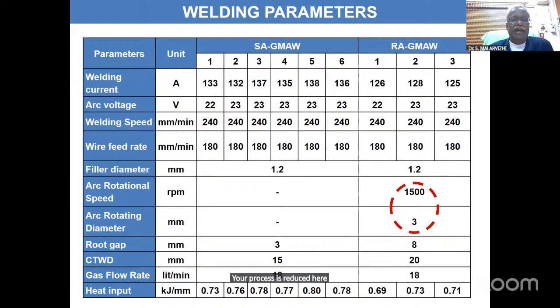And if you see the macrostructure of these two joints, the weld metal area in the stationary conventional GMAW is 205 mm square, but in the rotating arc it is 90 mm square, because only 3 passes are involved. Similarly, the heat affected zone area also reduces from 68.7 mm square to 22.6 mm square, so it reduces to one third. And the number of passes came down from 6 to 3.